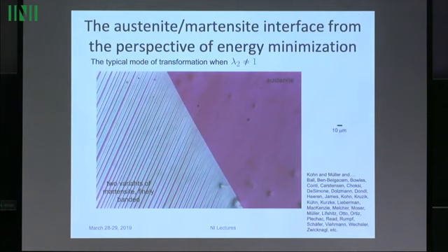So what is the microstructure? You see it at the transformation temperature. This, as it's labeled, is the austenite phase. In this material that I'm following through the lectures, it's a cubic crystal structure. These are 2 of the variants of martensite. So the deformation gradients in these bands fall very near 2 of the martensite energy wells. And this is a classic microstructure called the austenite-martensite interface.